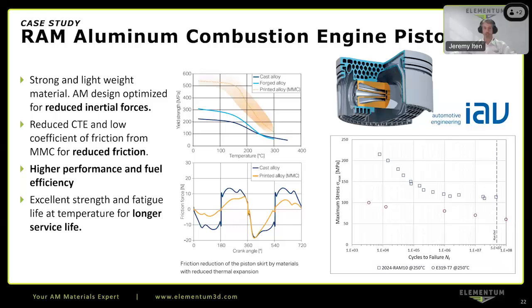The blue squares, in this case, are a 2024 RAM aluminum, whereas the red circles are a traditional cast aluminum alloy that's used for pistons. And basically what you're looking at here is the stress and the cycles to failure. At a much higher stress, you get much increased cycles to failure compared to the traditional cast aluminum alloy in this case. One other thing to mention is this fatigue chart is at 250 degrees Celsius, which is an operating temperature for these combustion engine pistons.